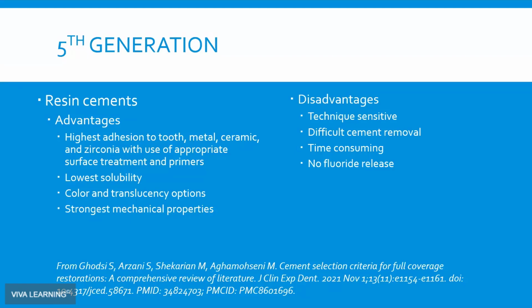Now, why would you have to bond these things? Well, unlike the soluble ones, which tended to be very dimensionally stable, if not maybe expanding slightly, resin, as we know, has a known shrinkage rate. And that shrinkage does cause, on an unbonded surface, some gap formation. I don't think that's a very controversial statement. In fact, if you don't use a bonding agent, it's highly likely the crown will just fall right off. So the priming of the various substrates was not optional.